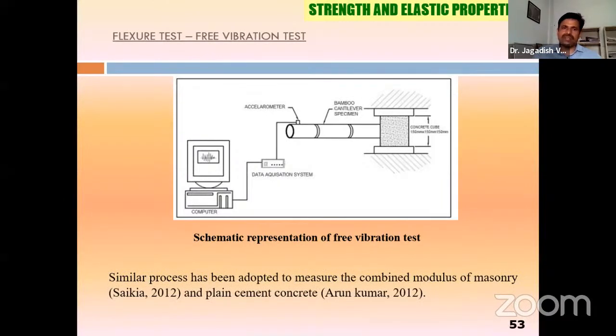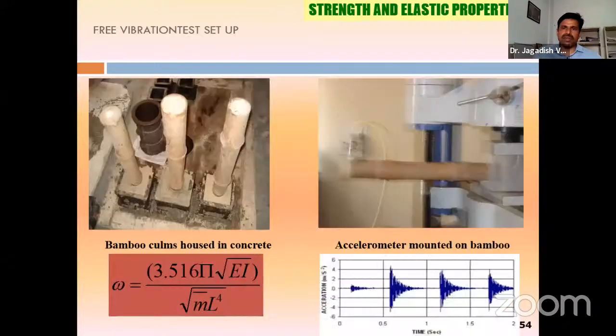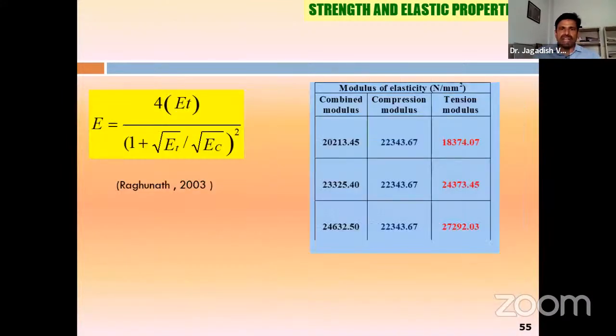This similar procedure has been adopted for masonry and plain concrete specimens. Here, you create a fixity on one side, and then you tap the other side of the bamboo, and then you fix the accelerometers. Using the accelerometer, you measure the vibrations, accelerations, and from that you can find the modulus of elasticity, the combined modulus.